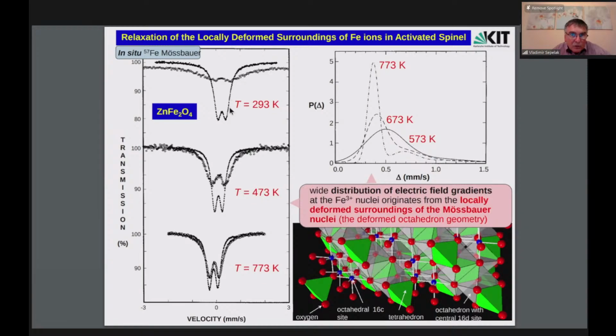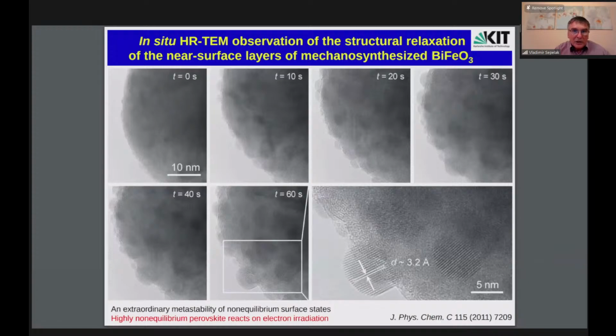You see here a spectrum for bulk material and a spectrum for mechanosynthesized material at variable temperatures. You see that with increasing temperature, the wide distribution of electric field gradients at the iron nuclei disappears, and the state after this temperature is comparable to that of bulk material. I already showed you that even irradiation of surface layers of mechanosynthesized material can induce a relaxation or crystallization effect.